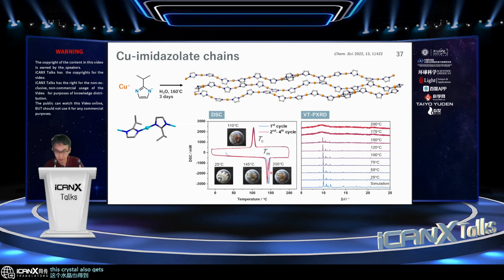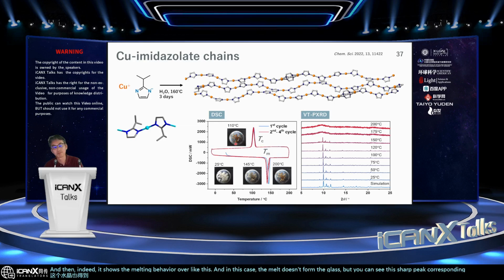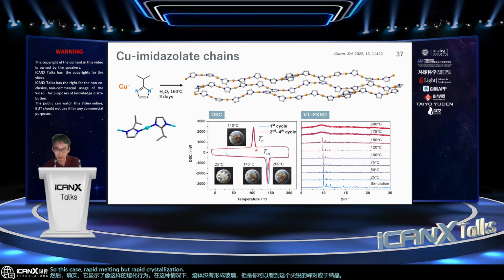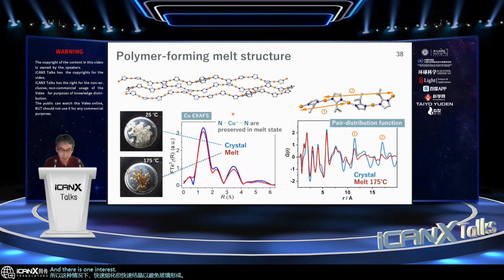And then indeed, it shows the melting behavior like this, okay? In this case, the melt doesn't form a glass, but you can see this sharp peak corresponding to crystallization. So in this case, there is rapid melting but rapid crystallization, which avoids glass formation. One interest is whether at the melt state this one-dimensional structure is preserved or not, okay? So we conducted X-ray absorption and pair distribution function measurements on the crystalline state and the melt state. The story is short: both structures are the same, which suggests that even in this viscous melt, the structure is completely composed of this one-dimensional structure without breaking the coordination bond.